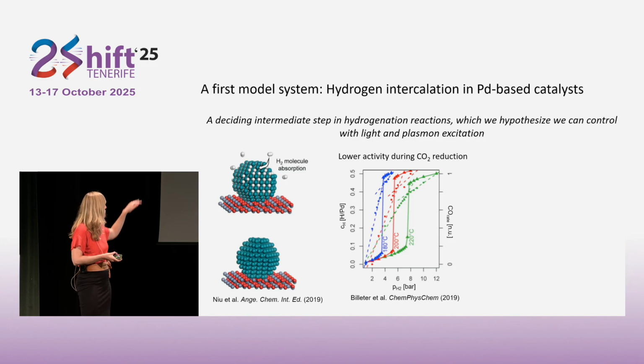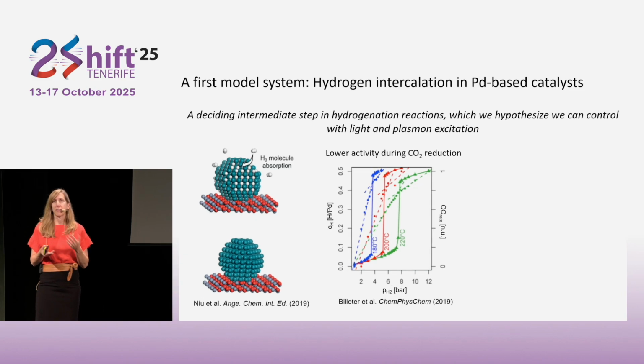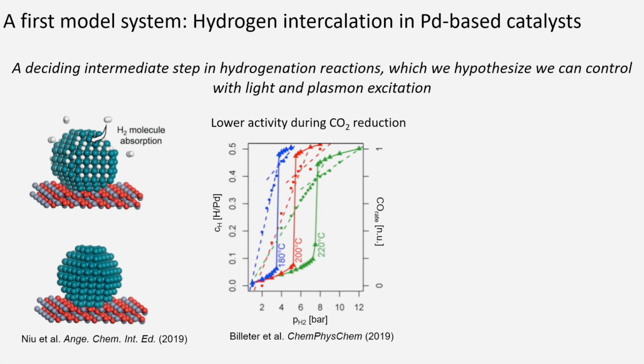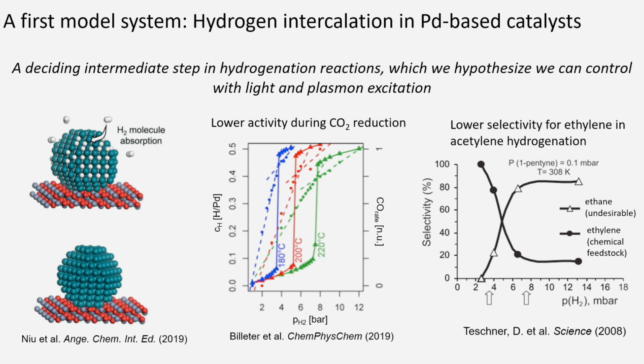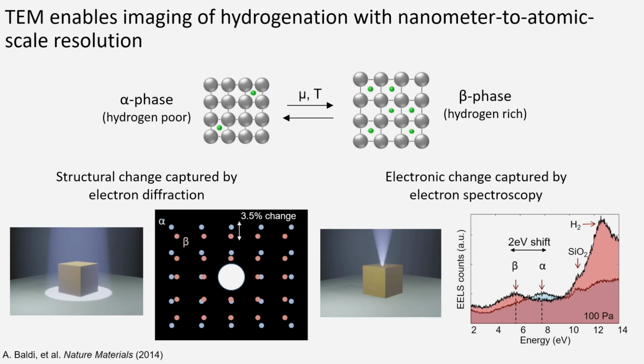So here are just a few examples showing, for example, that the catalysts that have been used for, say, CO2 reduction have lower activity once there's too much hydrogen that's intercalated into your nanoparticle. And you can also modify the selectivity. So I showed you earlier how with light we can control the selectivity and the activity. Here this is showing basically as you're controlling the pressure of hydrogen in your environment, you actually get an additional knob over the selectivity. So what we did is put some of these catalysts into our environmental transmission electron microscope and then just wanted to know how do they behave when there's only hydrogen. So there are no other reactants in this particular case.